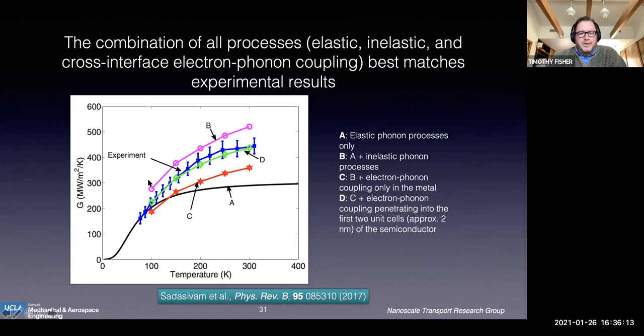So now, remember what we had before. The experiments here are blue. We kept green for the final result. But what we did is we sequentially added different transport processes. So we started out with curve A, which gives you only elastic phonon processes, and then curve B gives you elastic and inelastic processes, okay?